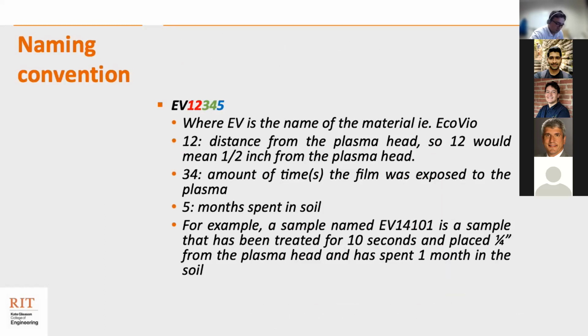How I've named the samples follows EV 1, 2, 3, 4, 5, where the first 2 letters correspond to the material name. Here EV is Ecovio. The next 2 digits correspond to the distance from the plasma head. Here 1, 2 would mean 1/2 inch from the plasma head. The next 2 digits correspond to the amount of time in seconds the film was exposed to plasma. Here, 3-4 would correspond to 34 seconds of plasma treatment. The last digit corresponds to the amount of time in months or days spent in soil. For example, a sample that is named EV14101 is a sample that has been treated for 10 seconds, placed quarter of an inch from the plasma head, and has spent 1 month in soil.